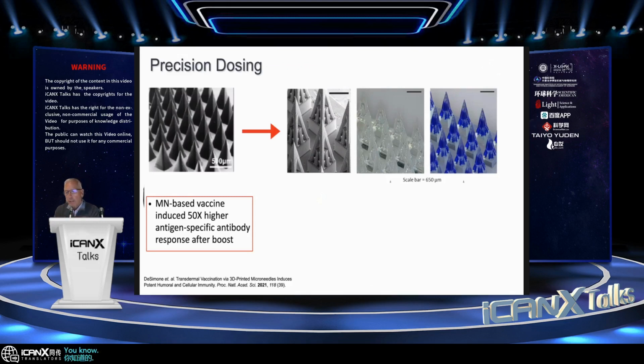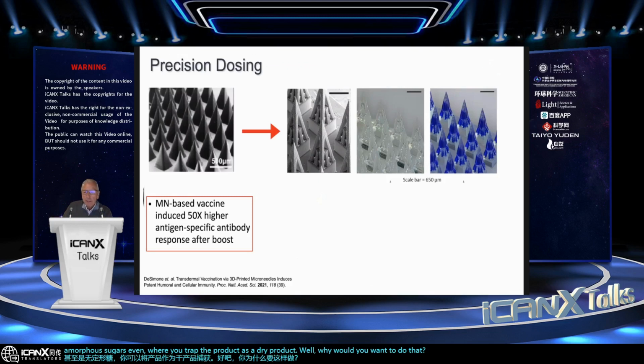Or, and more excitingly, we could freeze dry that liquid, lyophilize it, and now we can have a solid product that might be mechanically fragile, like a cake of sugar, which is the typical lyophilization media. It doesn't have good mechanical properties, amorphous sugars even, where you trap the product as a dry product. Well, why would you want to do that? Well, maybe that was a lipid nanoparticle vaccine formulation. Lipid nanoparticles in liquids are not stable for long periods of time. Remember during COVID, the cold chain issues. There was more talk about freezers during COVID than I think I've ever seen in my life. The challenge of global supply chains.